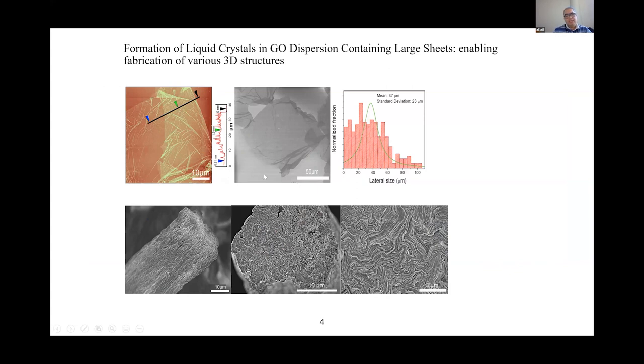So over my PhD and a little bit of the first year of my postdoc, we learned that if we synthesize graphene oxide with very, very large sheets, they form liquid crystal. And then because of that, you can process them in the way that you can process polymers. We made some fibers, for example, from them. The fibers were conducting and high surface area, so we could use them as the electrode in applications where surface area was important.